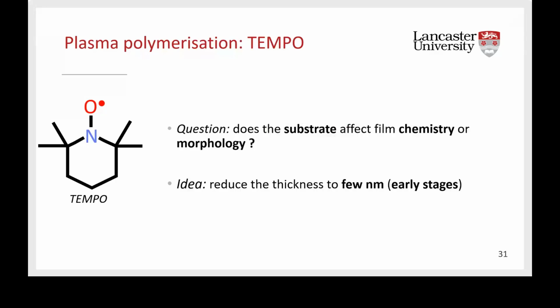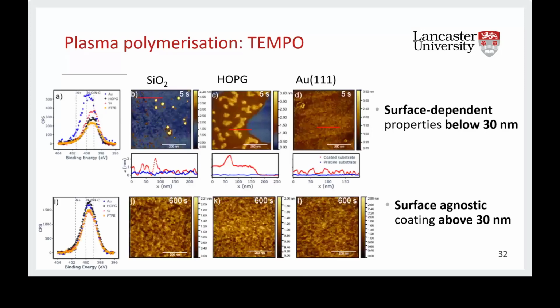In my research, I'm trying to understand how the substrate affects the chemistry and the morphologies of this TEMPO coating. To do so, I need to reduce the thickness down to a few nanometers. And in this slide, you can see the results. In figures B, C, and D, you can see some TEMPO highlighted in this brown-yellow color on different surfaces highlighted in blue: silicon oxide, graphite, and gold. And you can see very different morphologies in figures B, C, and D. So actually, the morphology is surface dependent when the polymer is very, very thin.